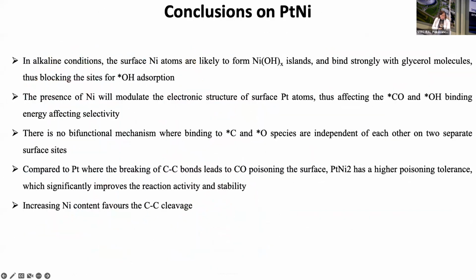This pretty much says the same thing, and I just want to summarize this here, that basically in alkaline conditions, clearly nickel on the surface will form nickel hydroxide, and it will bond strongly with glycerol molecules, and they will block further oxidation and further OH adsorption. So nickel modulates the electronic structure, and it will really affect how these intermediates are binding. There is no bifunctional mechanism here. And as I said, compared to pure platinum, where there is a lot of CO poisoning, here there's less CO poisoning, particularly for this platinum nickel 2, which has a very high poisoning tolerance and also has the best selectivity towards the product that we want.